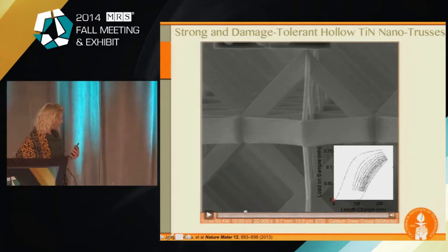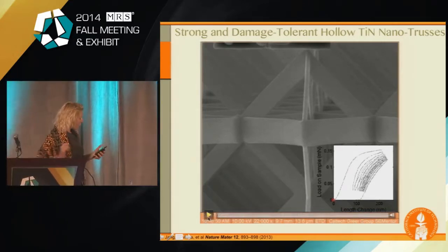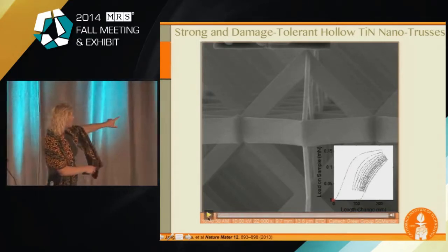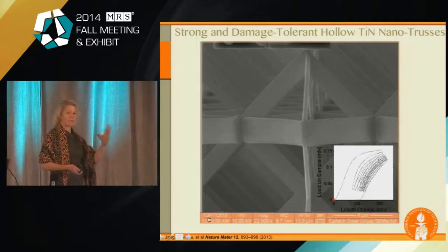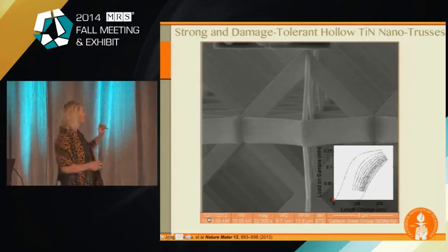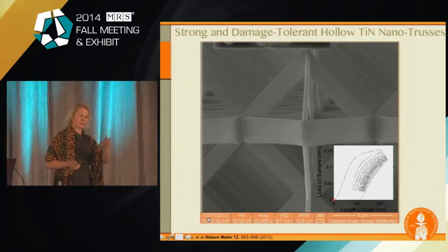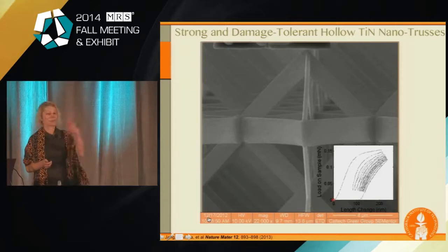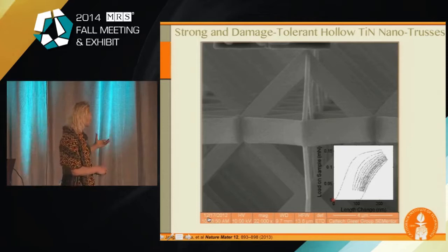This experiment we did before the compression of the full nanolattice like I showed you. So what Dongchen did is he made this out of titanium nitride. So that's also a brittle ceramic, and these are also hollow. Now he's going to compress only a single unit cell. Okay, so this is, again, a brittle ceramic, it's hollow. I think the wall thickness may be on the order of 75 nanometers or so, and he's going to compress it. So it should absolutely shatter, right?